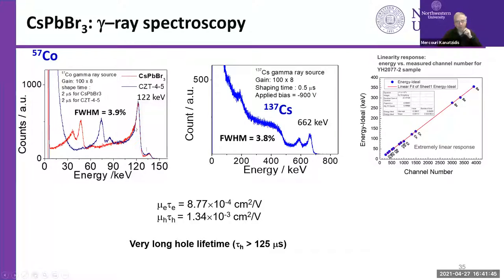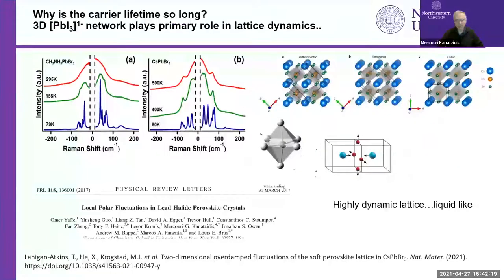I need to point out that these spectra are collected with hole collection, right? We're measuring the holes, not the electrons, in this spectrum. If we try to measure the electrons instead, we do not get as good a resolution. So this is unlike CZT, where one measures the electron response; here we measure the hole response. That's a big difference. We also found that the hole lifetime is very, very large, more than 125 microseconds. So this material is very